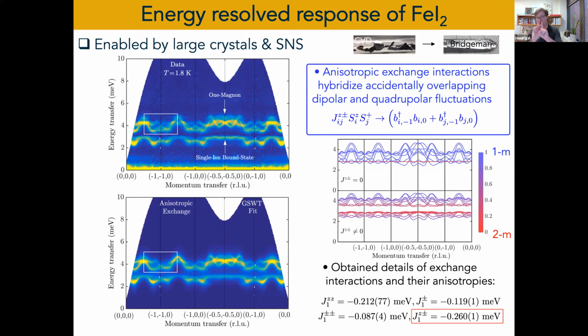Now, there's one thing I want to say: when we plug in this Jz±, which you see here is the dominant interaction, what this does is that it tilts the plane of the ordering of the spins with respect to the triangular plane. And that tilting, from our calculation, should be 13 degrees. Back in the day, when people did the diffraction on these materials, they assigned the spin to be on the C axis. Now we're going to do some diffraction to see if indeed the spins are tilted 13 degrees. This is really the effect of Jz±. It's tilting the spin space with respect to the triangular plane. So we expect to be able to see this in diffraction.